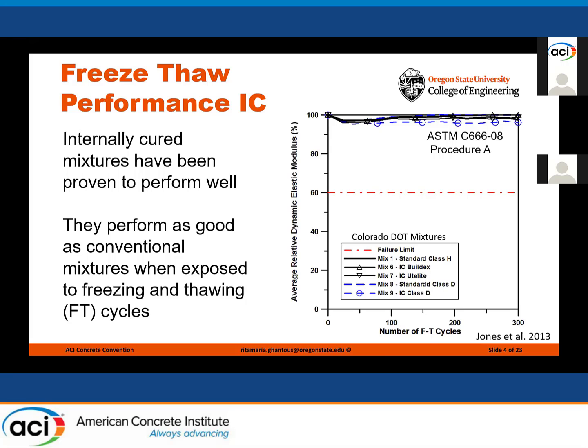And this graph shows results for mixtures with and without internal curing. All the results, as you can see, are similar. The lines are on top of each other. And that means that all the mixtures perform similarly and resist freeze-thaw cycles.